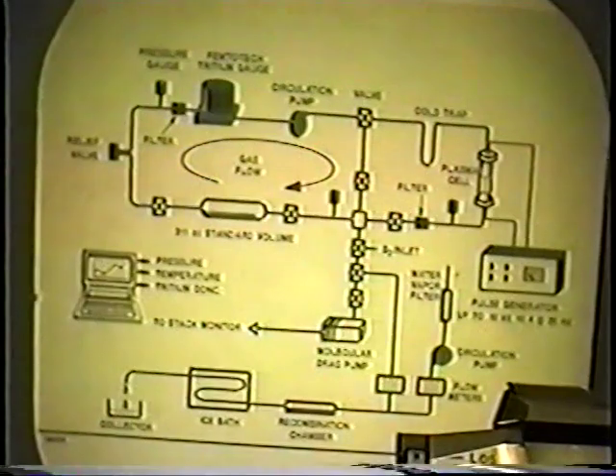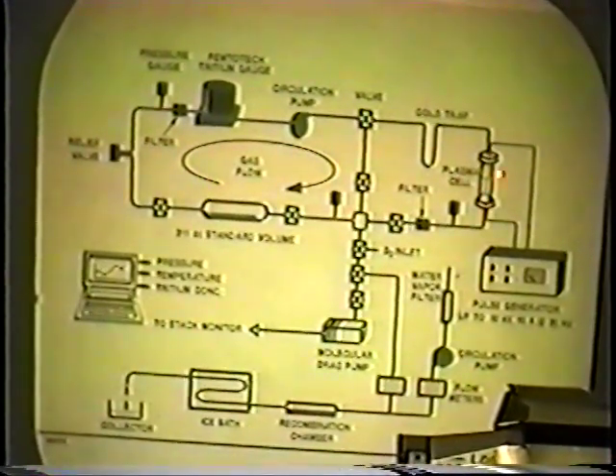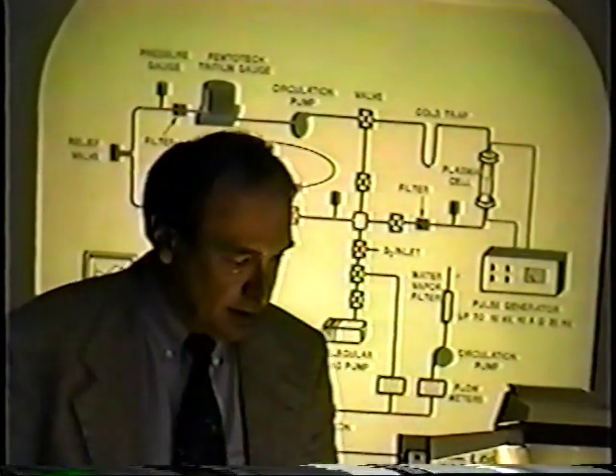Okay, this is the canonical tritium measurement system that we have. We have the plasma cell here. We flow the gas around through the cell. We're putting on a mass spec so that we can look at the gas concentration now and the impurities in the gas. We also, in the last year, put this little water collector system on, so we determine what the tritium is in the D2 independently, and then compare it to the FemtoTech in all cases where we've looked at the drop in the reading and we've compared it. It's been within, say, 50 ppm of what we expected. So that's pretty good.